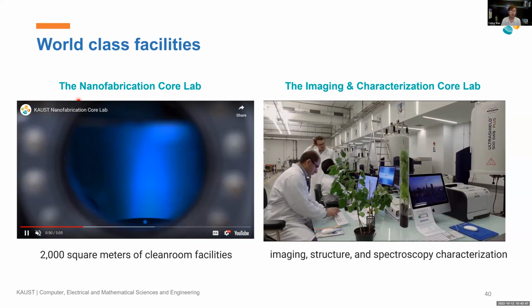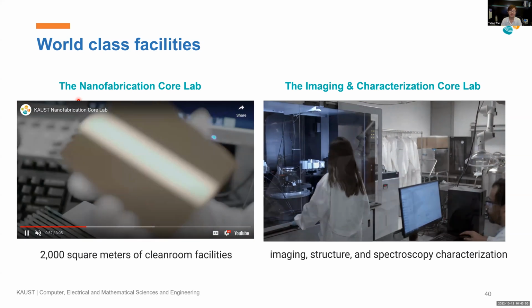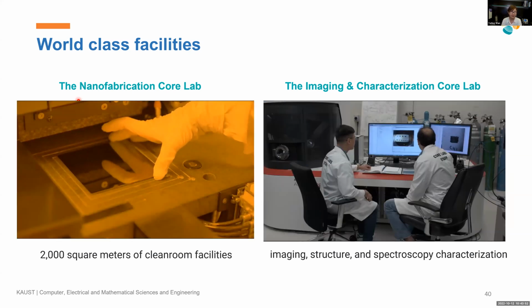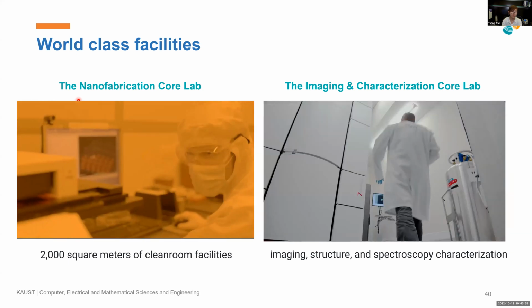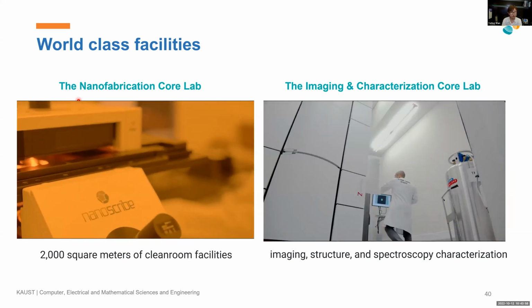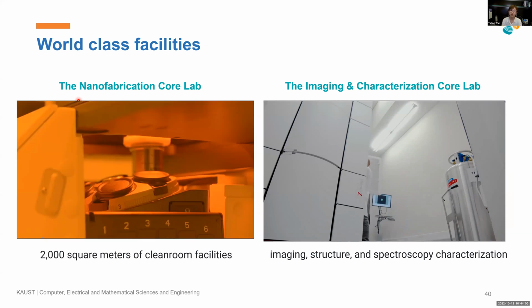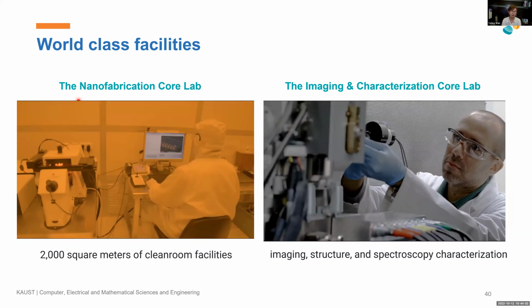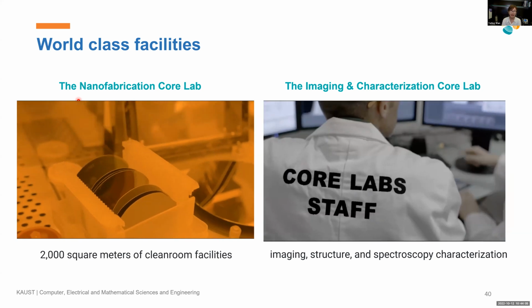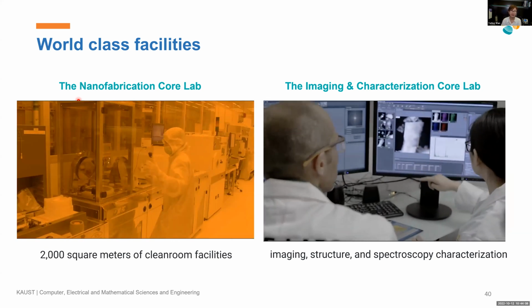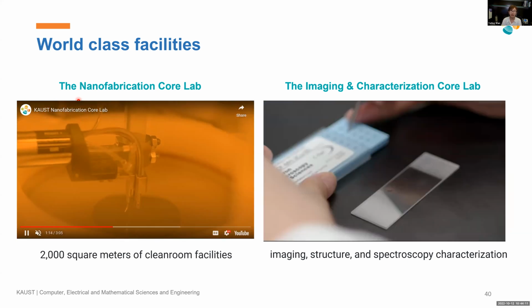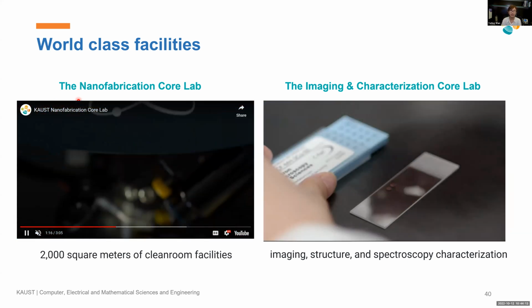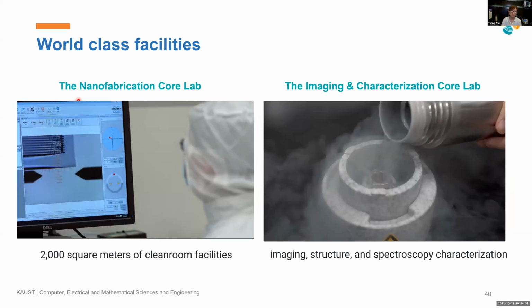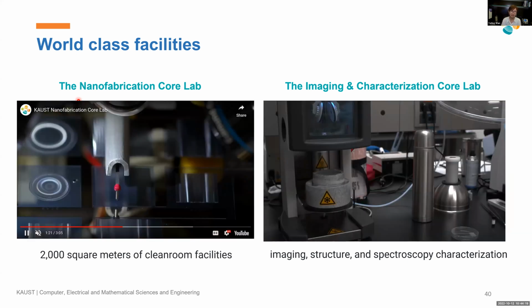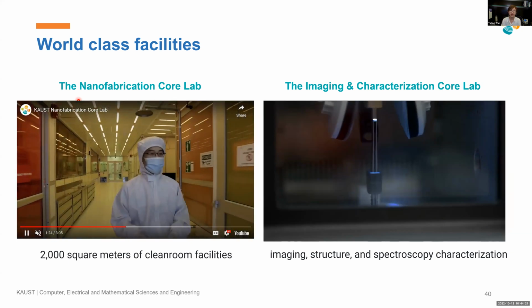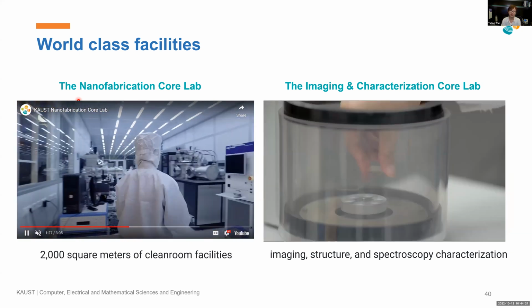There are many new equipments that are not shown in this video. For example, the newest maskless aligner from Heidelberg that will be installed this year, which is able to expose a 100mm wafer in about 30 minutes and achieve minimal feature size around 0.5 micrometer, with overlay accuracy better than 200 nanometer. And the newest Oxford Cobra etcher, the 100 Cobra, will also be installed around the same time, which is very good for etching in phosphide, gallium arsenide, and gallium nitride-based materials, in addition to atomic layer etching process.